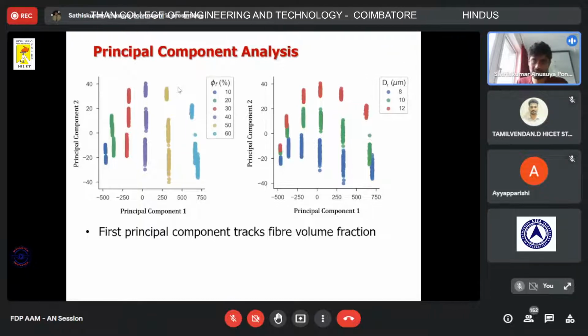For example, the first principal component tracks the fiber volume fraction. The second might track the fiber diameter. The third might track the fiber distribution, or the spacing between the fibers, and so on. And if you go to higher and higher order, the meaning may not be obvious, but it still characterizes some of the microstructural features.